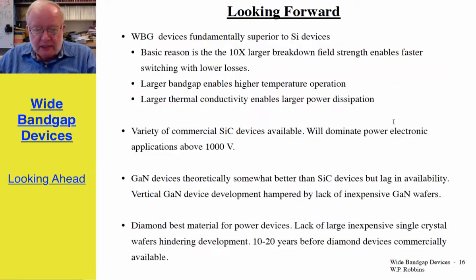So what does this all mean? I think we've convincingly demonstrated that wide bandgap devices are fundamentally superior to silicon. The basic reason is the 10x or more larger breakdown field strength that enables faster switching with lower losses. The larger bandgap enables higher operating temperatures, and the larger thermal conductivity provides the ability to dissipate more power in the device without exceeding the temperature limitations.